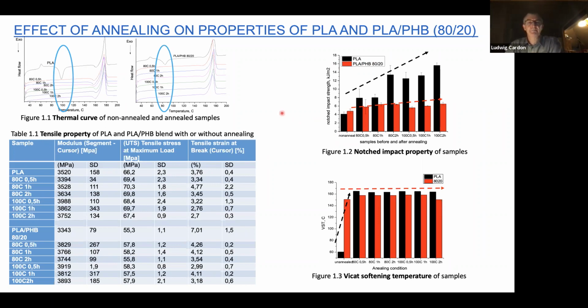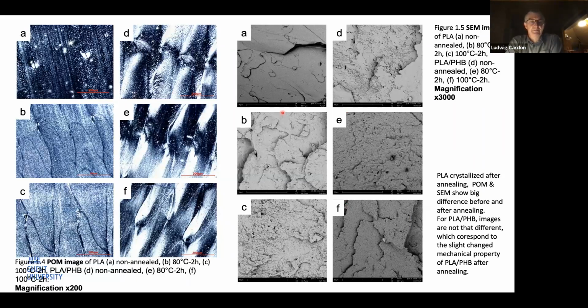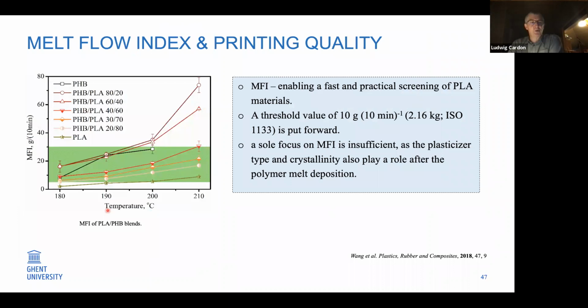So briefly some images to highlight how we then investigate the brittleness or the composition or the interlayer adhesion of the different materials. So I mentioned already the melt flow, the green region is acceptable, even above 20, but most optimal is the melt flow index as an indication point for fast identification instead of viscosity measurements. So a melt flow of 10 is a somewhat ideal processing environment.